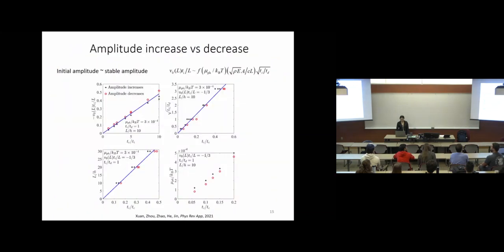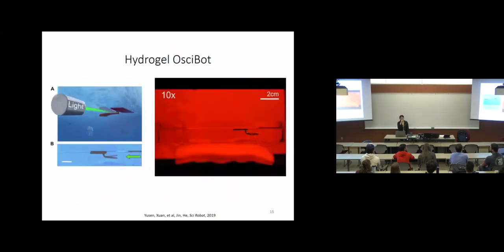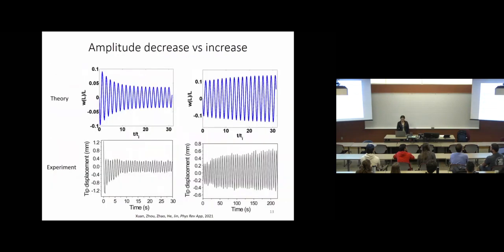Yeah, so for this hydrogel, actually you see those videos, those are real time. So the frequency typically is around 1 hertz. Yeah, 1 hertz. So here you can also see it's around 1 hertz. So I would say, first of all, for hydrogel, the time scale is typically long because it requires diffusion. But for this one, you don't require diffusion through the entire thickness, but mainly on the surface, and moreover, in this material, we indeed have some way to speed up its diffusivity. So therefore, it's relatively fast compared to other available hydrogels.